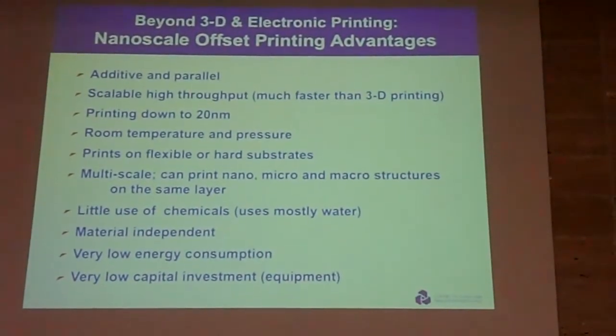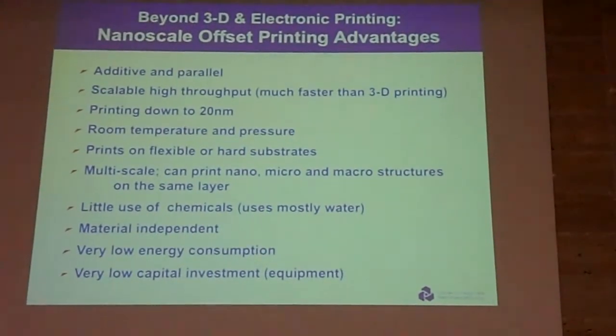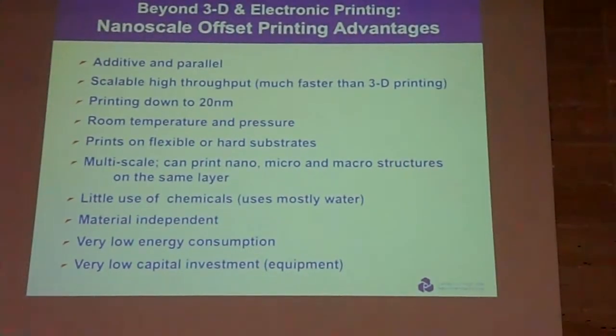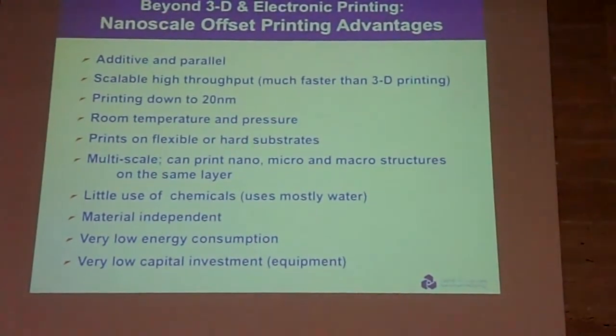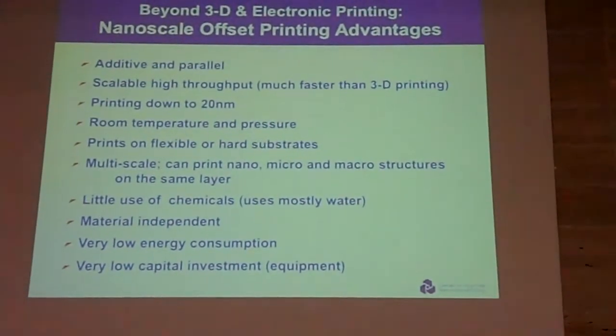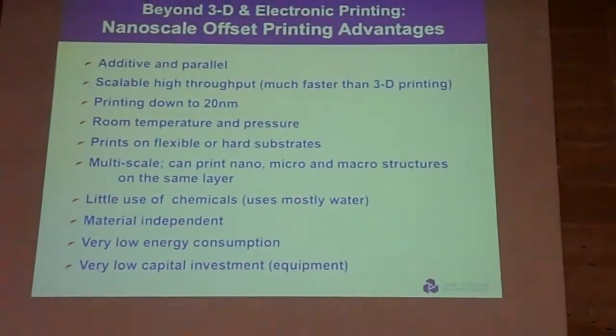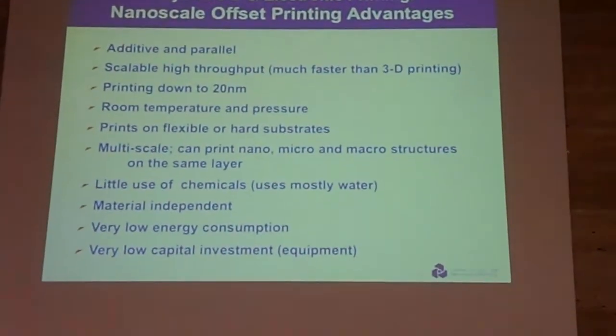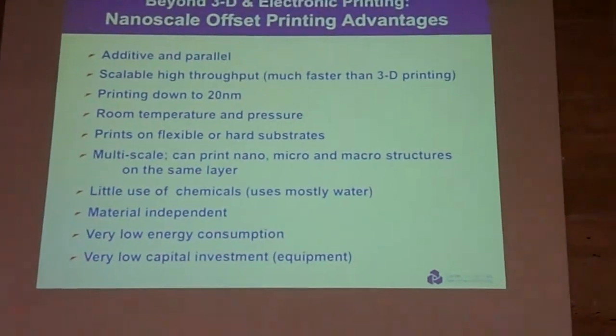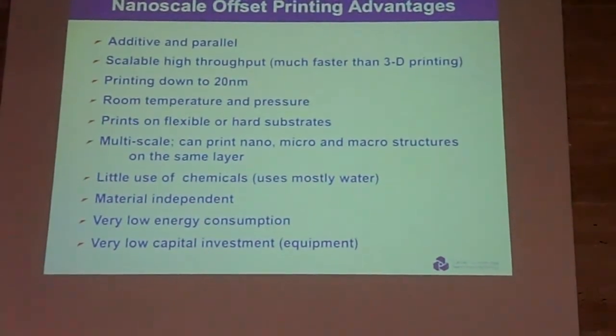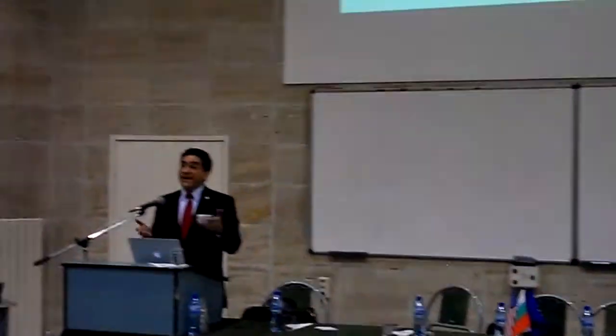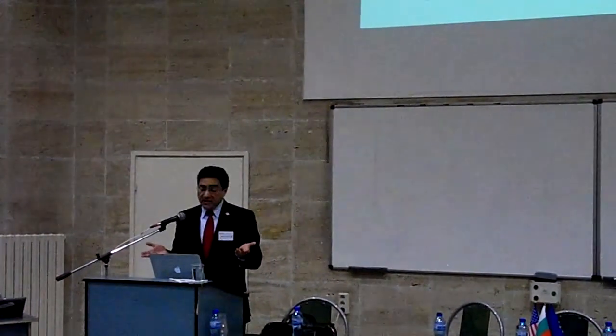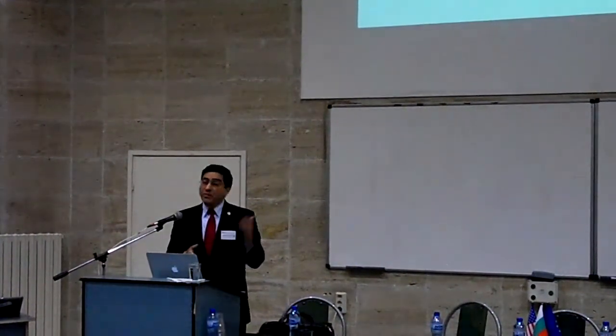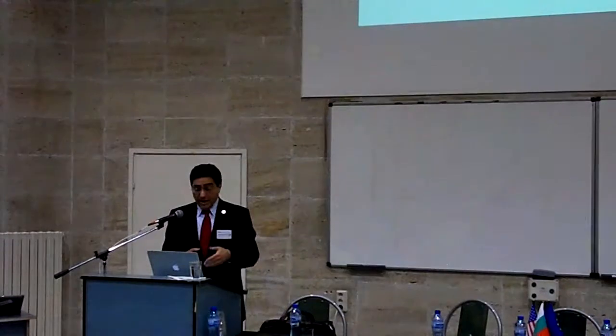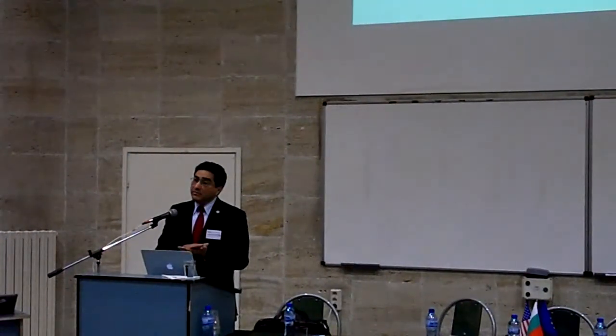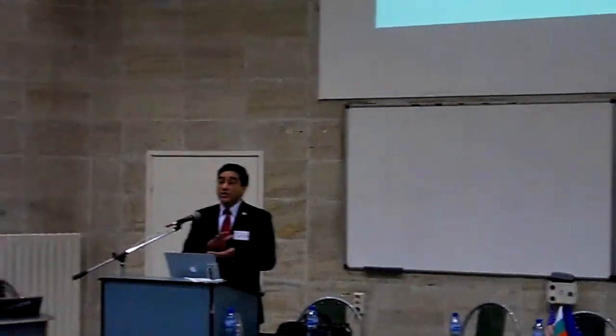So compared to typical manufacturing, you save about half of the processes, because usually you add and remove, add and remove. Here you just add. Okay? Also, this is room temperature and room pressure. If you compare that to conventional electronics manufacturing today, they use vacuum and very high temperature processes. And you can print down to 20 nanometers. You can print on polymer or silicon or any other substrate.